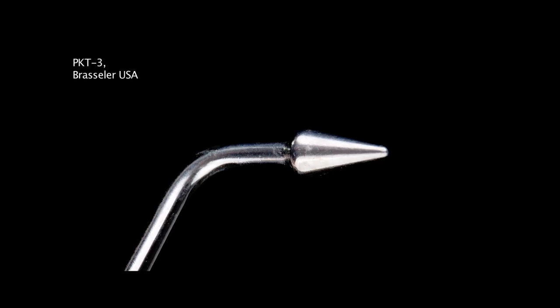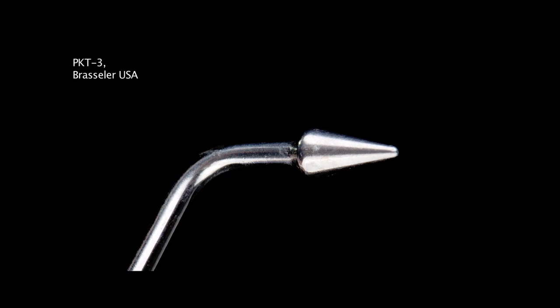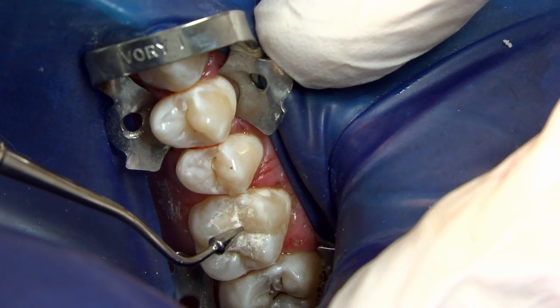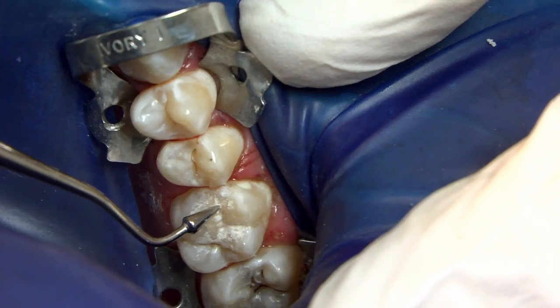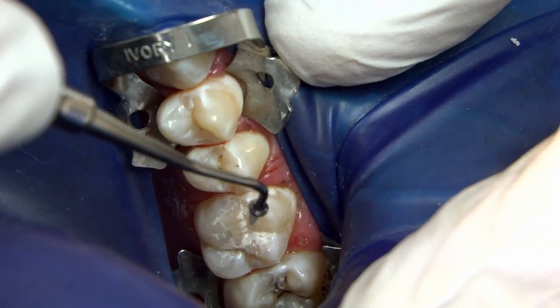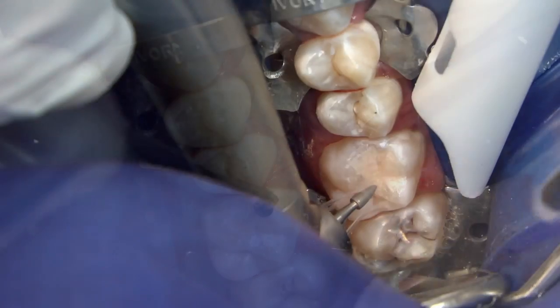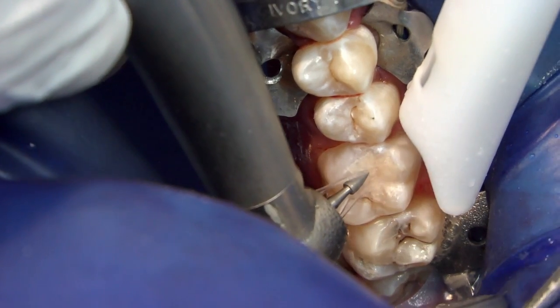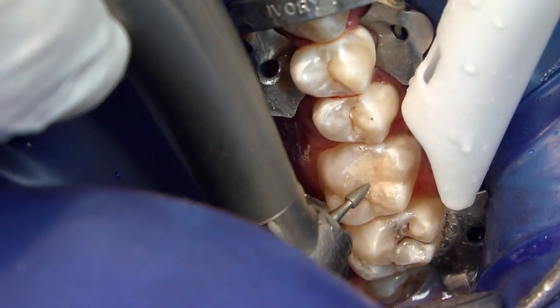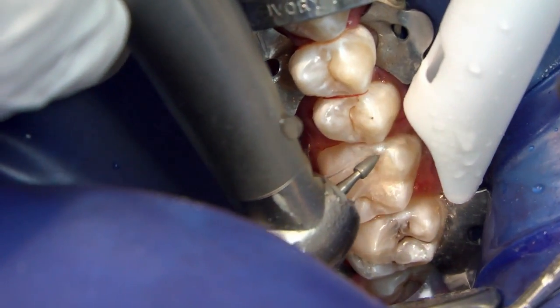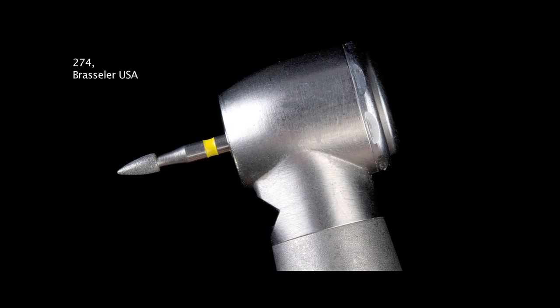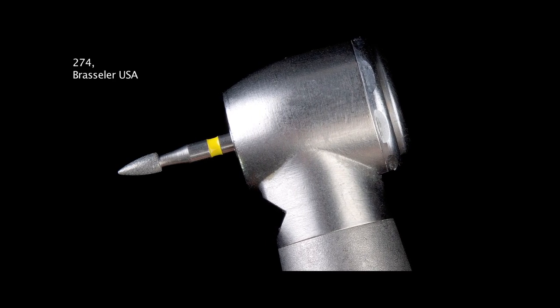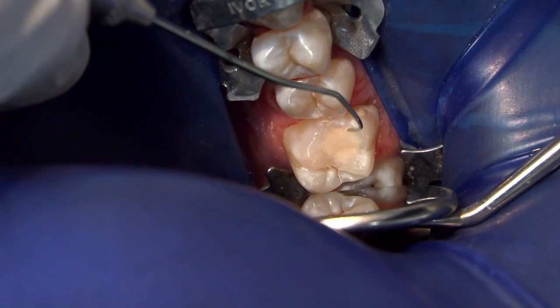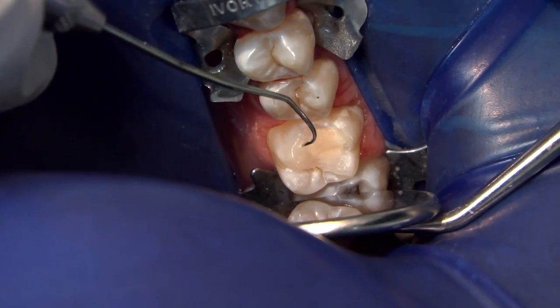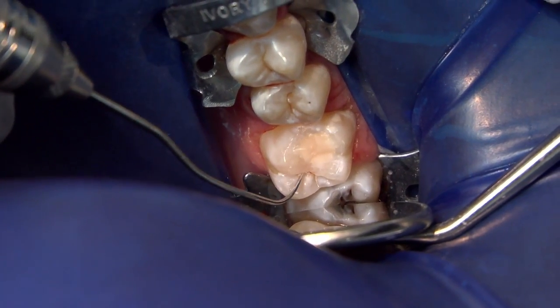Next, a pyramidal-shaped instrument, the PKT-3 by Brasseler, can be used to establish optimal anatomical contours. In 3.5 minutes, with the completion of the cement set, the occlusal contours and the restorative interface are refined with an 8-micron tapered diamond bur under a water spray. The restorative interface is inspected with an 11-12 explorer to ensure marginal integrity.